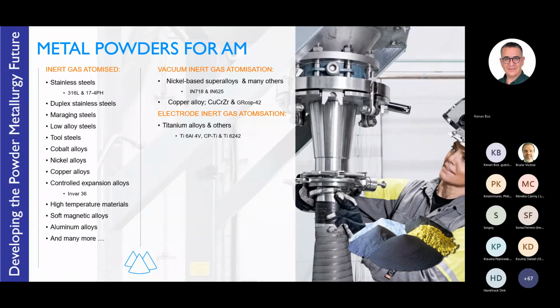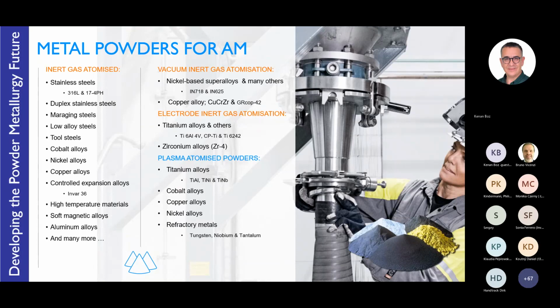Of course, the workhorse of this aerospace industry is titanium 6 aluminium 4 vanadium, as well as commercially pure titanium and alloys related to the aerospace industry like titanium 6242, which have a slightly higher strength than titanium 64 and operate at a higher temperature also. Zirconium alloys as well are also possible and used in the nuclear industry. And then plasma atomizing: titanium powders, titanium aluminides, titanium nickel like shape memory alloys, and titanium niobium. Cobalt alloys, copper alloys, nickel alloys, as well as refractory metals, tungsten, niobium, and tantalum. And there are many others. And one final process to mention is the hydride-dehydride process for manufacturing titanium alloys.